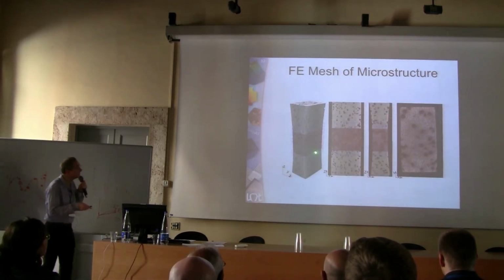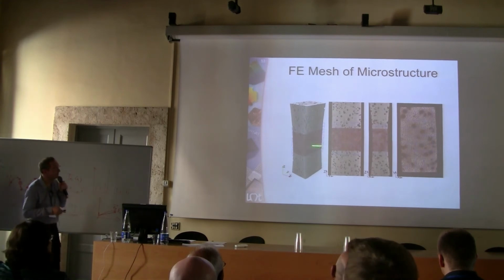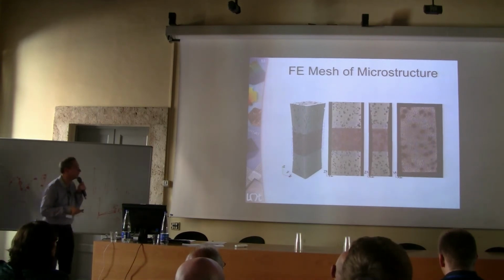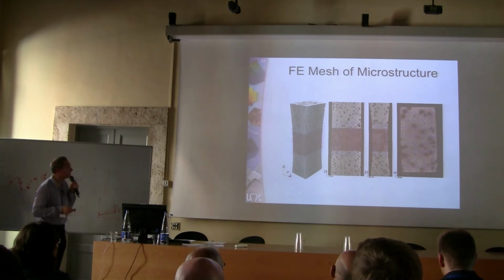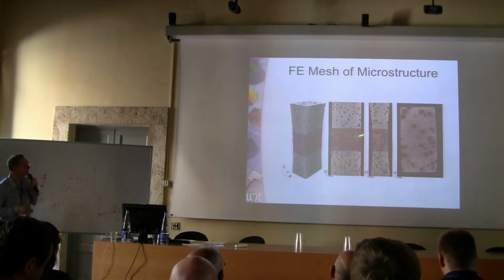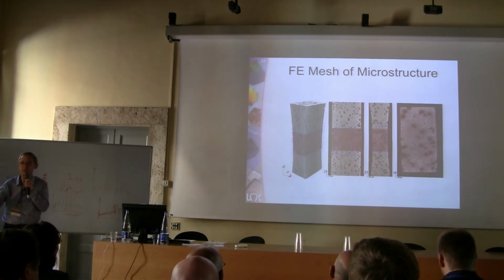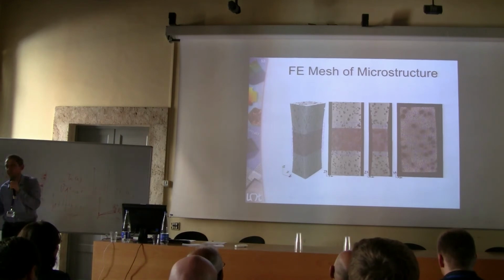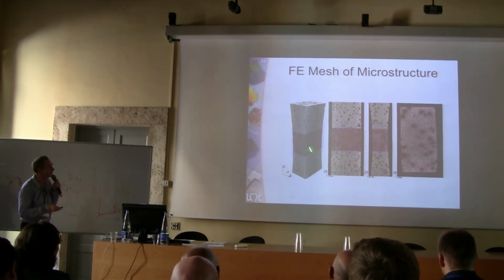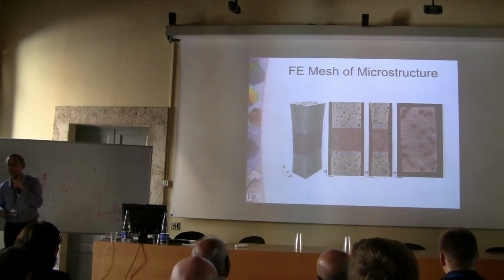And so this is the example on the sample we were studying. So here you see two meshes: the red one, which is the one that is consistent with your microstructure, and the blue one that was actually used for DVC calculations.